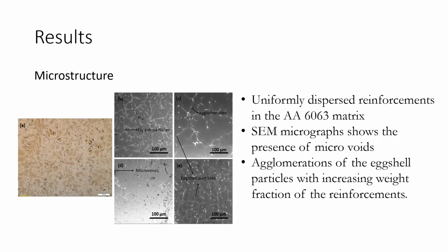With the result of the microstructure, we could see that the reinforcements were uniformly dispersed in the aluminum matrix, and this was due to the employment of the two-step stirring technique. Also evident in the same micrographs for the reinforced samples was the presence of microvoids, and these microvoids were developed during the solidification of the cast. Agglomeration of the eggshells was also pertinent in the samples.